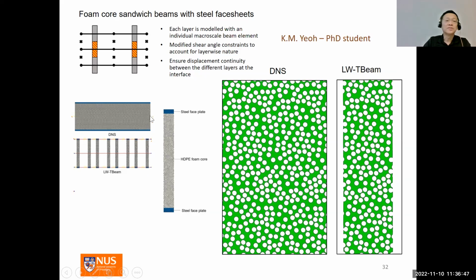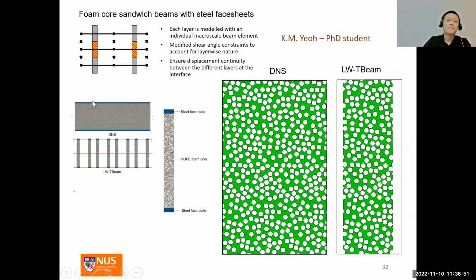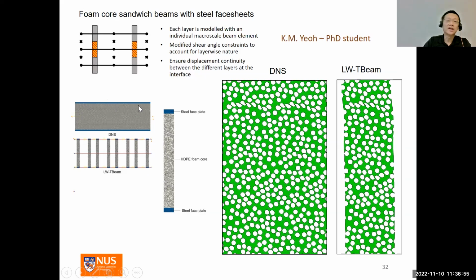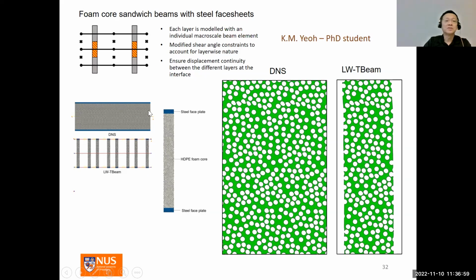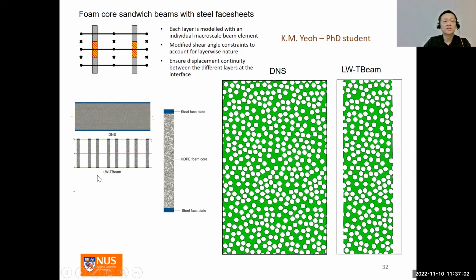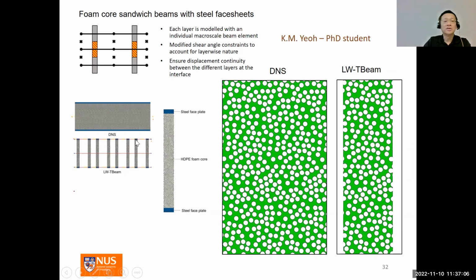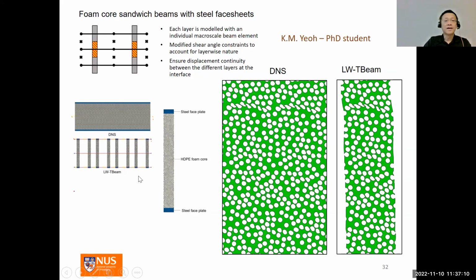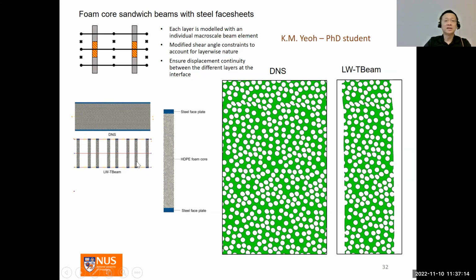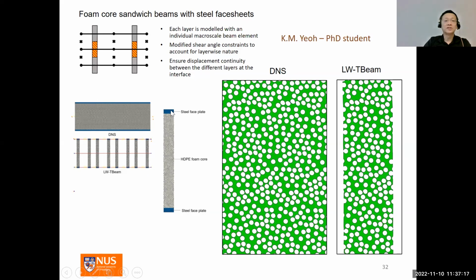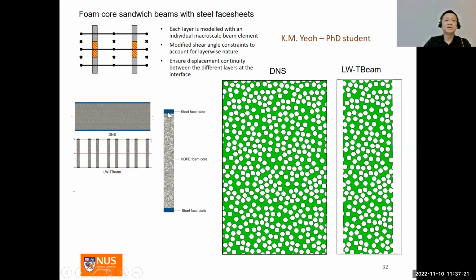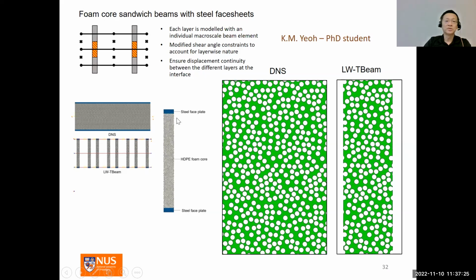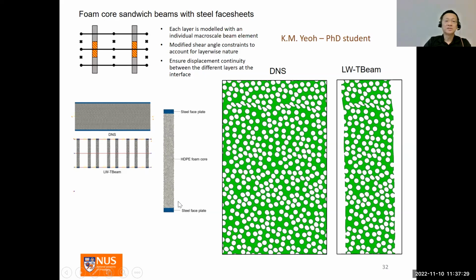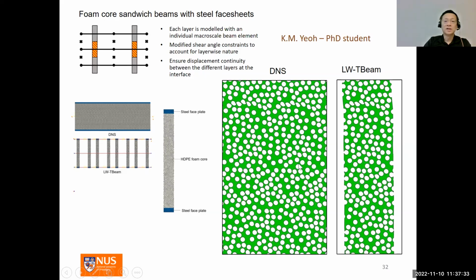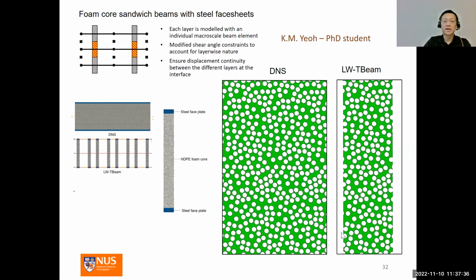Although this appears like a block of gray rectangle, it's actually a very, very fine finite element mesh. Below here is the layer-wise beam element. Each of these strips represents the RVE, the representative volume element at the Gauss points. This is what the RVE looks like. The problem is a sandwich beam with steel face plates here and there, and then this is the foam core. The interesting thing here is that if you look at the deformation of the